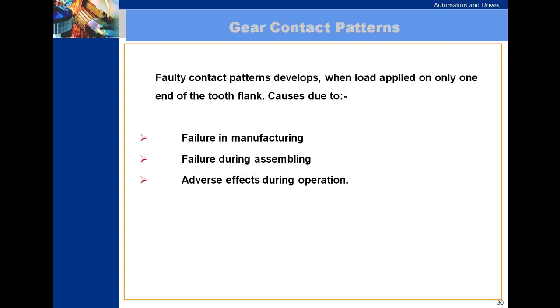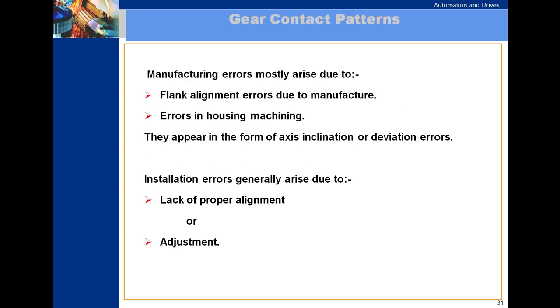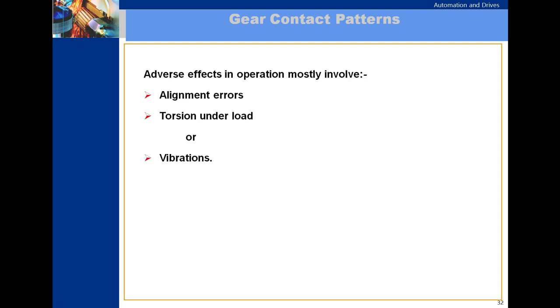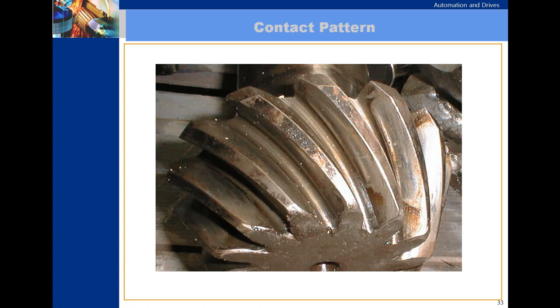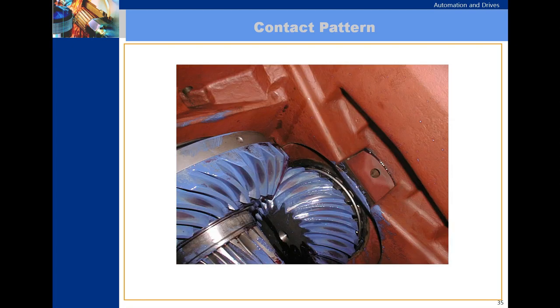Gear contact patterns. Faulty contact patterns develop when load is applied on only one end of the tooth, caused due to failure in manufacturing, failure during assembly, or adverse effects during operation. Manufacturing errors mostly arise due to flank alignment errors and errors in housing machining. They appear in the form of axis inclination or deviation errors. Installation errors generally arise due to lack of proper alignment or adjustment. Adverse effects in operation mostly involve alignment errors, torsion under load, or vibrations. In the contact pattern, you can see here, only part of the tooth flank is worn out, matching tooth contact.